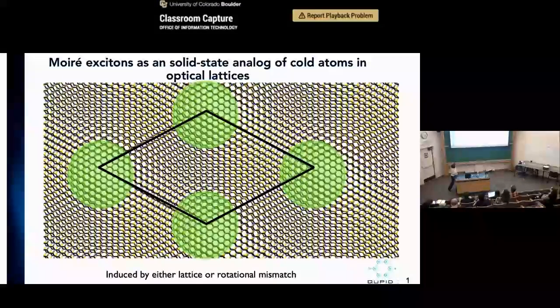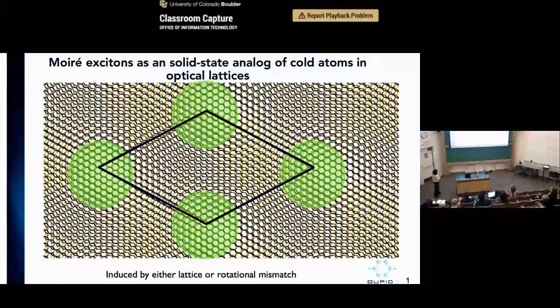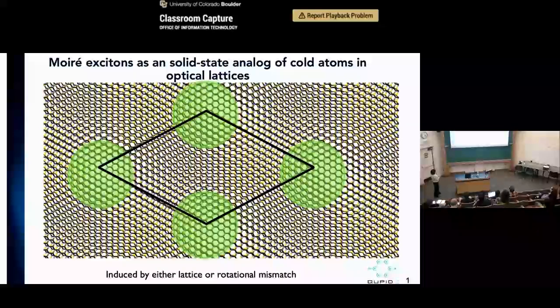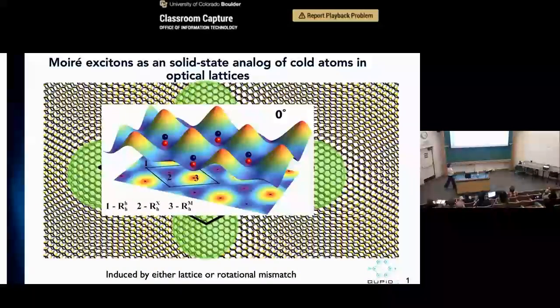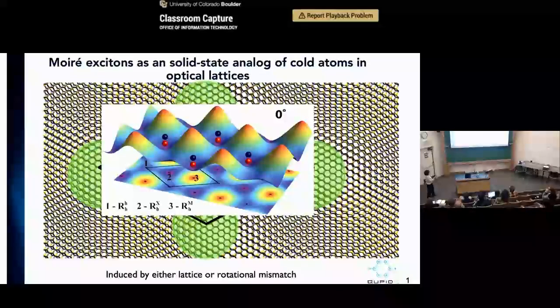As you can maybe see, in this green dot that I highlighted, which is a high symmetry point of this new Moiré superlattice, the hexagons are right on top of each other. But if you move away from it, the structure changes and the hexagons are slightly offset. What this does is create a spatially varying potential for the excitons. Instead of the exciton freely moving in a single layer, you create a trap for the exciton at certain locations of the lattice, and now your excitons are trapped in this lattice, very similar to how you use an optical lattice to trap atoms.